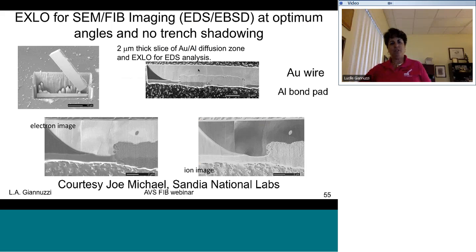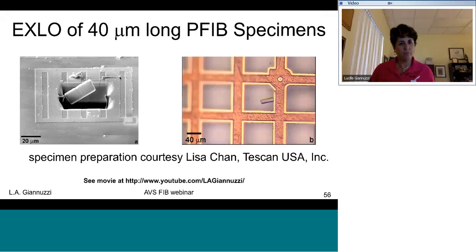And Joe Michael, again, uses this technique routinely for lifting out thicker samples to do EBSD, top-down SEM EBSD. And this way you can optimize your collection angles also, so that you can do, for example, SEM EBSD, top-down perpendicular to interfaces, or I should say parallel to interfaces, rather than at some tilt of the electron beam at some tilt to your sample surface. You can lift out bigger samples, so 40 micron long sample, for example, so you can do this using your plasma FIB samples, not a problem.